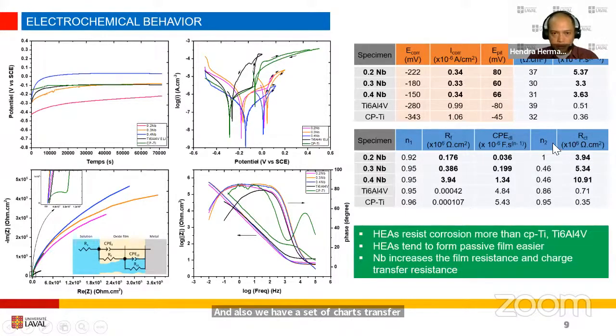And from all this result, with some analysis, we see that high entropy alloys resist corrosion better than commercial pure titanium and Ti6Al4V. The high entropy alloys tend to form passive film more easily than these two titaniums. And the effect of niobium is that it increases the film resistance and charge transfer resistance, as you can see from the electrochemical impedance spectroscopy result. Okay, so those are good news.